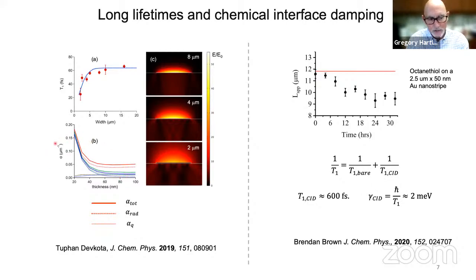This is a plot of an attenuation rather than the lifetime, so it's essentially the inverse of the lifetime. This is done for nanostripes that have different widths. So I think 2, 4, and 8. Actually, the 2 is at the top, then the 4, and then the 8, and also different thicknesses. Okay, so what this plot shows is that the attenuation gets much stronger as you make the nanostripes smaller, either as you make them thinner or as you reduce the width. Okay, so you reduce the dimensions, the lifetimes go down. And that's what we see here, right? That the lifetimes go down as you reduce the width.